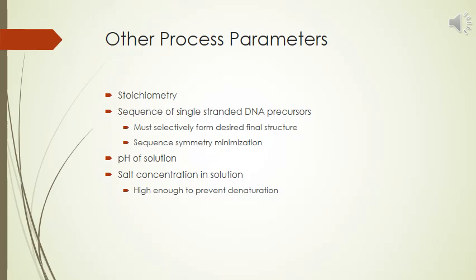Hence, the self-assembly process should be performed in an aqueous environment with a sufficiently high salt concentration and a pH buffered around neutral.